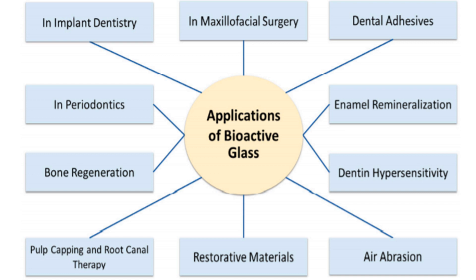Bioactive glasses have many applications in dentistry, some of which include their use in dental adhesives. Since some versions of bioactive glass can deposit fluoroapatite, they can be used as dental adhesives in orthodontic treatments to solve the issue of white spot lesions. Care should be taken with the addition of fluoride since its amount affects mechanical properties. Bioactive glasses are also used in adhesives since the deposited hydroxyapatite, when in contact with dentin, reacts with the tissue inside the dentinal tubules, resulting in dentinal adhesion and providing a stronger bond.